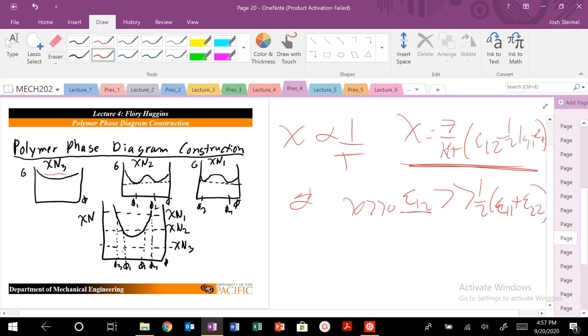So low values of chi mean high temperature — we should be in the mixed state. Inside this curve, we are in the demixed state, and we can see that from these free energy curves. My free energy curve here is all concave up, no points of inflection, no common tangents — I know I'm working with a material that is mixed.